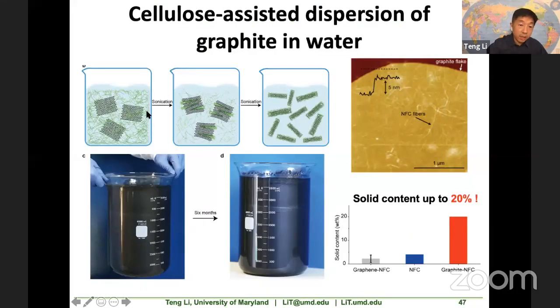The way it works is we start with graphite. Graphite is cheap, graphene is too expensive. Now we mix the graphite and the cellulose nanofibers in water, just water, no other chemicals. The cellulose nanofibers actually carry surface charge. When you do the sonication, the cellulose nanofibers manage to exfoliate the thick graphite flakes into very thin ones. We measured that the final thickness of the graphite is around 3 to 5 layers. And the cellulose nanofibers are wrapping around these very thin graphite flakes.